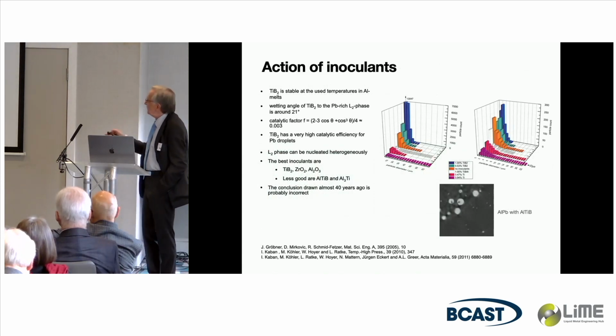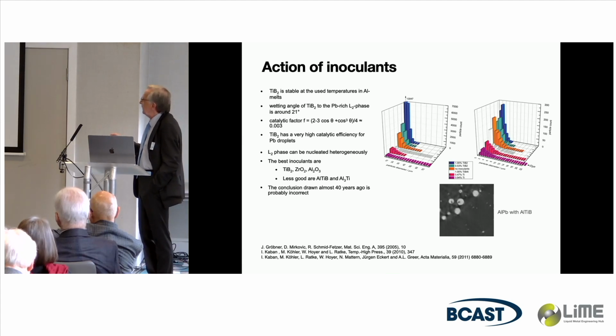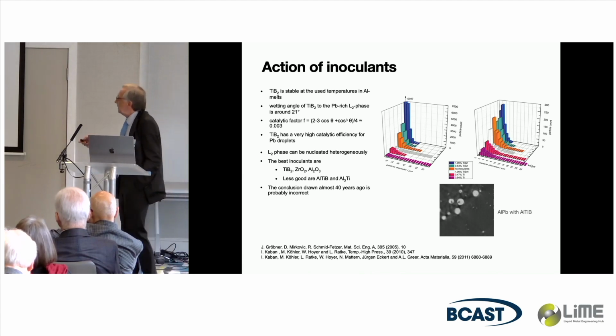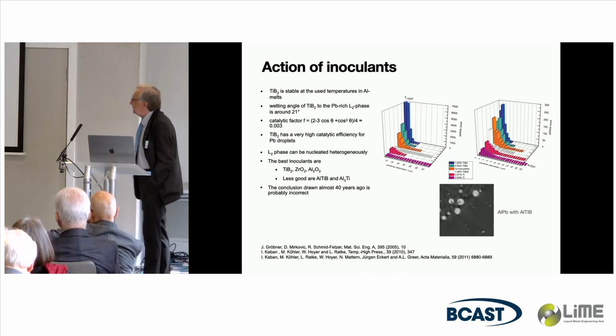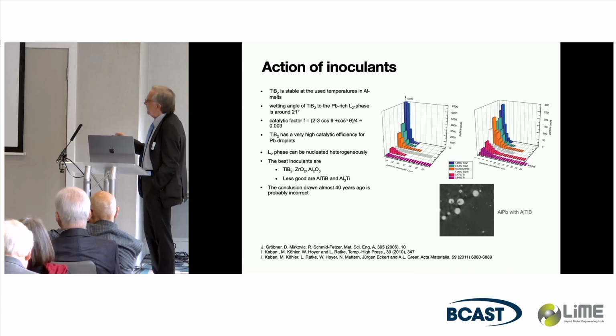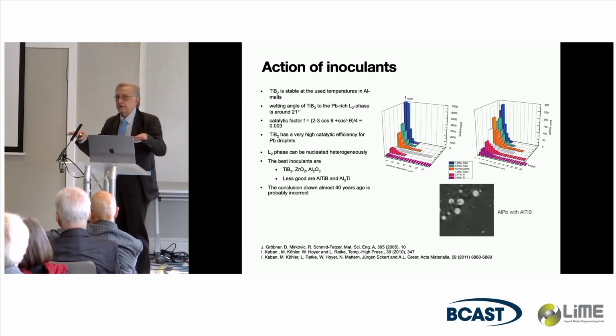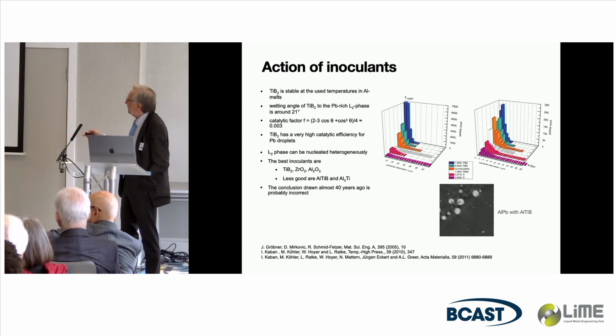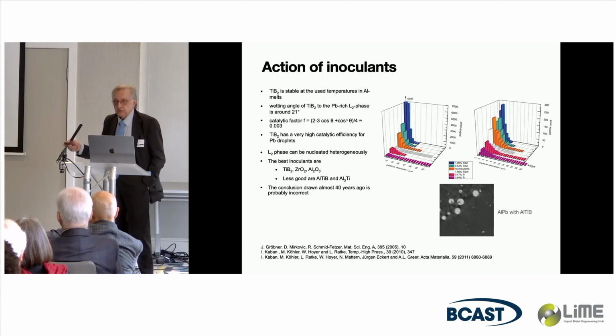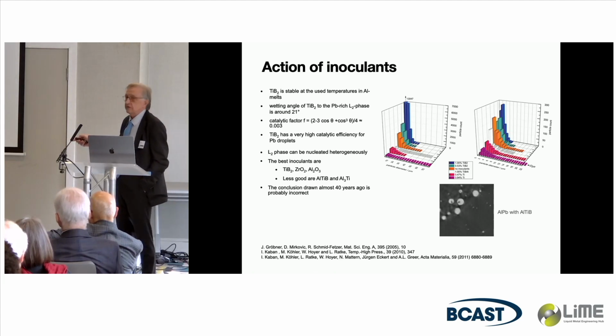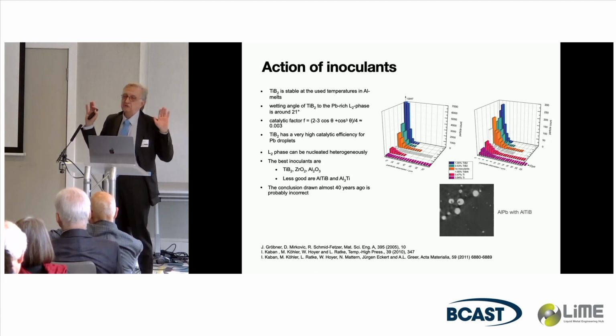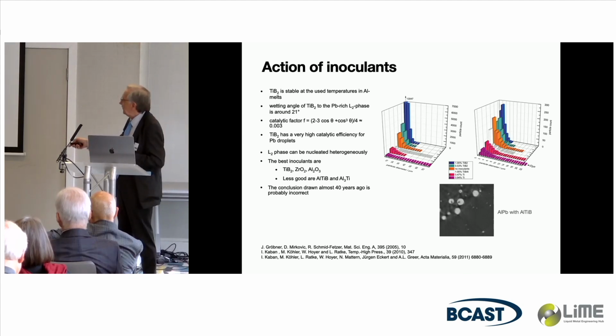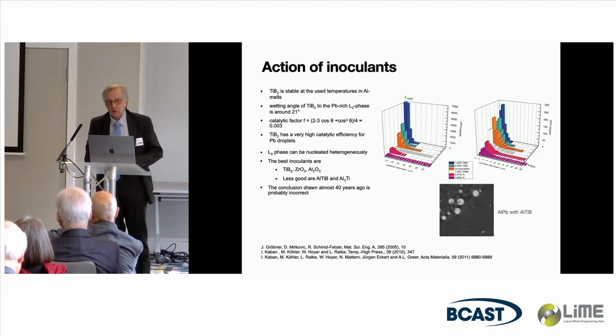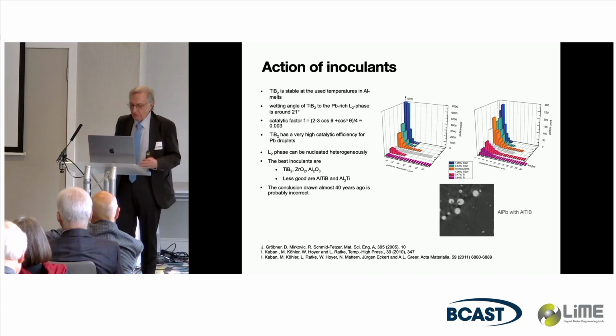We later looked into that in much more detail and could show, especially in the papers with Ivan Kaban, who was at that time in Chemnitz, now he's in Dresden, that he measured the wetting angle of the lead-rich phase on a plate of titanium diboride and could show the wetting angle is very small, so the catalytic factor you calculate is also very small. Well, it's heterogeneous nucleation. Our conclusion we had drawn years ago is simply not correct.